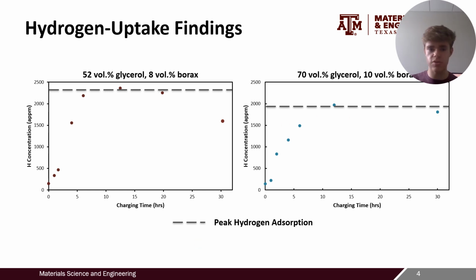So this maximum concentration was significantly higher using the lower volume percent glycerol, and this seems to indicate that its higher viscosity may slow the diffusion of hydrogen throughout the solution. So previous work has been done charging nickel with a water and sulfuric acid-based electrolyte, which actually experienced lower hydrogen concentrations than either of the two glycerol borax-based solutions being shown. So this indicates either solution would support the formation of a nickel hydride through proper hydrogen adsorption, which is really great news because that's what we're shooting for with these experiments.